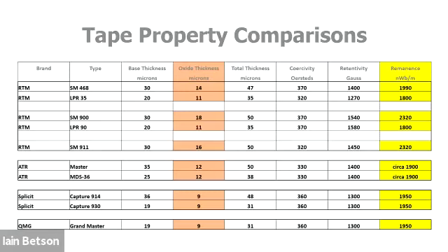If you're using your tape in a domestic environment, perhaps you're putting a few reels on, you just want to record and basically you're on a budget for a long record time, well then you could use something like an LPR, long play record, I assume that stands for LPR. If you look at those top two columns from RTM, SM468 and LPR35, they actually are the same formulation, but they're just painted on differently. If we look at our oxide thickness in microns, there's 3 microns thinner oxide on the LPR35, the base thickness is thinner, and the overall total thickness is 47 and 35.